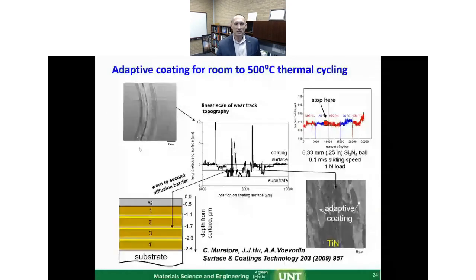All right, so now we did this. Of course, you can also do more engineering. You can add more of these diffusion barrier separation layers, and now you can start talking about thermal cycling, or at least a few thermal cycles, and try to maintain the friction coefficient low as you go between, in this case, 500 and 25 C through this adaptive mechanism. Now we're covering the low temperature and the mid temperature. Now let's go to the high temperature.